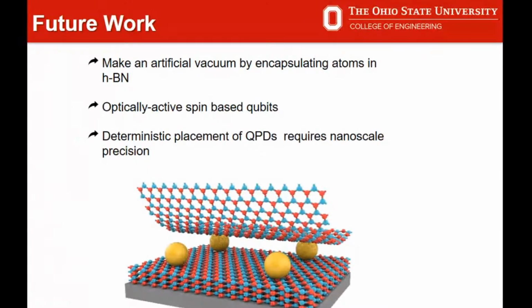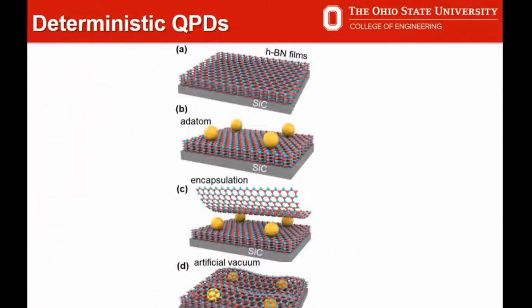So again, we are thinking about it in an experimental domain. In the theoretical domain, we are also working on it, but it's very tough, but we are hopeful we could do it. So this is the whole schematic diagram, starting from figure A, B, C, and D. Figure A shows that we'll be growing the hBN thin films on top of a silicon carbide substrate. After that, we are using an adatom like, say, gold or something like that, which will just sit on top of the film without penetrating it. So it's not substitution. If you know the concept of doping, it will always substitute an atom. But here it will just adsorb on top without creating any kind of penetration.